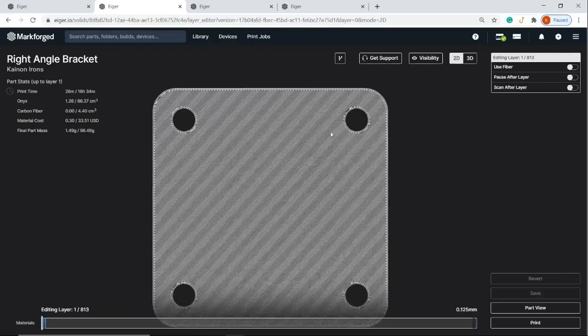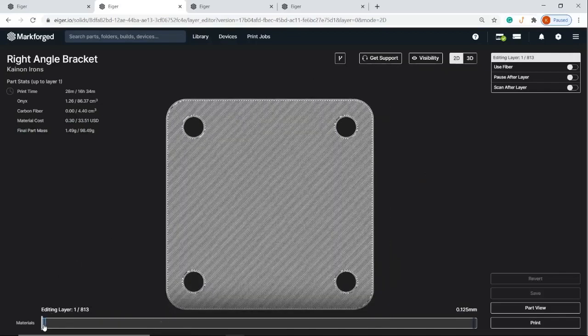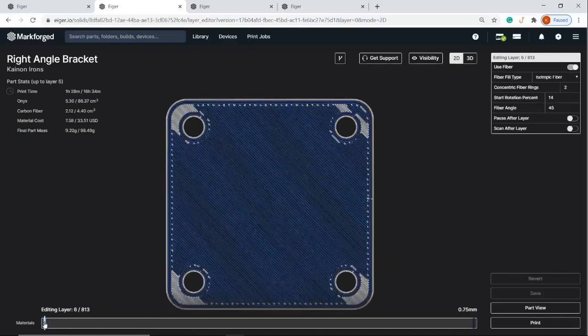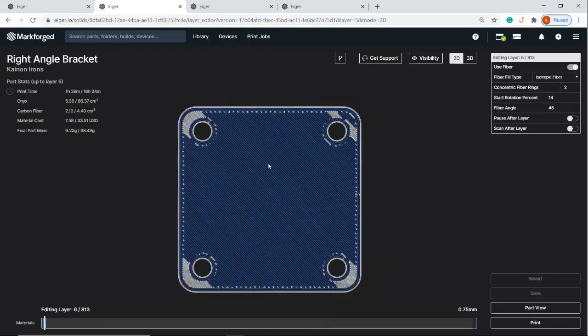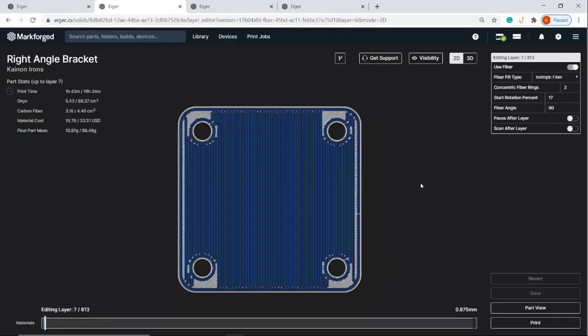And so here's the base of the part. That's going to be your onyx material, and that's one of those floor layers. And as we build up, Eiger automatically will lay out fiber on the bottom and the top of the part. And that goes back to that sandwich panel theory that we looked at earlier, where you're getting the most strength at the extremities of the part. And take a look at how the fiber is naturally oriented. And so it looks like we have about 6 layers here, and we have an isotropic fill pattern. And the angle of the strands in this case is at 45 degrees. But as you work your way up, you see how that angle changes. And again, you could customize each individual panel based on layer and the type, whether it's isotropic or concentric.